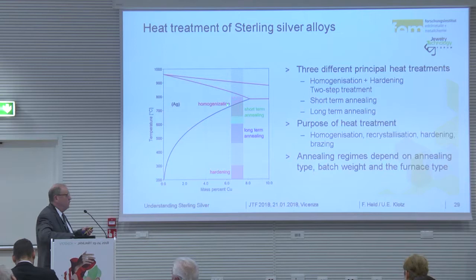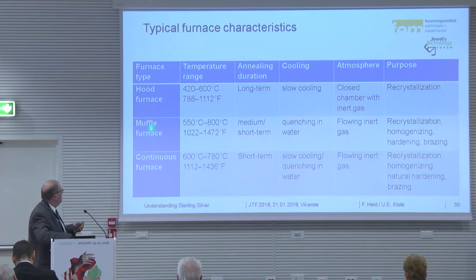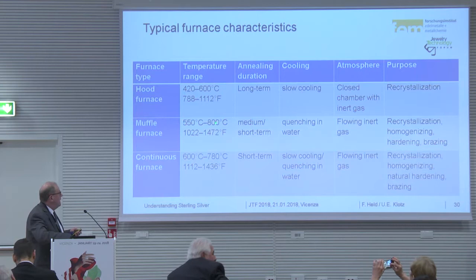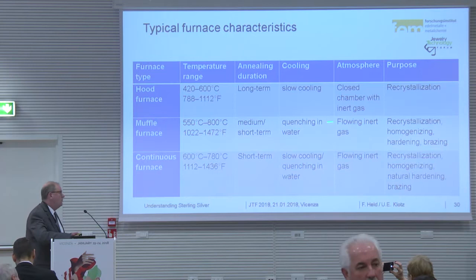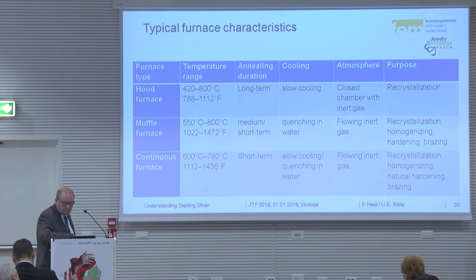Whether it is short-term or long-term annealing depends on the furnace we use. We have a hood furnace with a lower temperature. Long-term cooling is slow cooling, in a closed chamber with inert gas, and we use it for recrystallization. We have the muffle furnace, temperature up to 800 degrees, medium short time, quenching in water, flowing inert gas, and we use it for recrystallization, homogenization, hardening, brazing, and the continuous furnace. This is short-term annealing, slow cooling, quenching in water, flowing inert gas, recrystallization, homogenization, natural hardening, and brazing will do there.